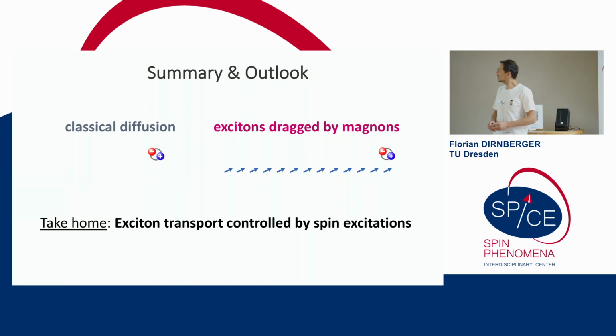In principle, I think the direction of this work is interesting in this sense: controlling the motion of excitons is not that easy. If you have electrons, you apply an electric field, you make them go left, you make them go right, whatever you want. Excitons are charge-neutral optical excitations, so it's not very easy to control them. People have tried many different approaches, and a lot of them work too. So here we're thinking that maybe spin excitations, controlled excitation of spin waves, even using more traditional excitation schemes, might be a very nice way to direct the motion of these excitons in magnetic semiconductors.